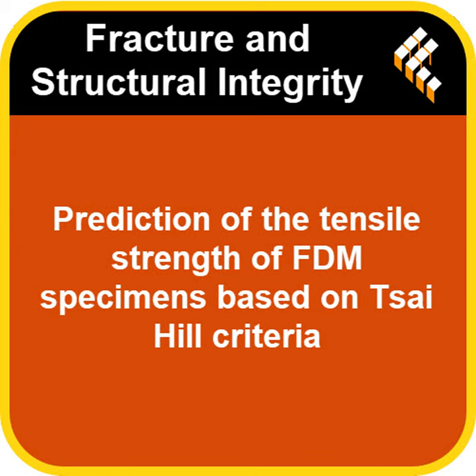Adding that outer contour made a big difference for those 0-degree parts under shear. That outer shell acted like a reinforcement, really enhanced the performance, and helped prevent those layers from just sliding apart too easily. So the shell was key there. It really seemed to be. They saw the cracks starting within the specific area designed for the shear test propagating through the layers. Okay, so for shear, that contour was a real game changer for the 0-degree alignment.